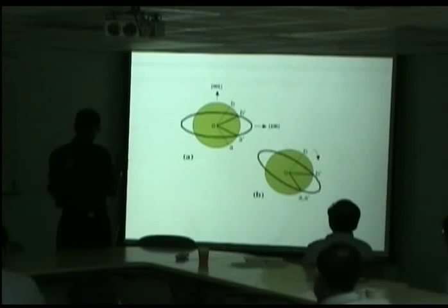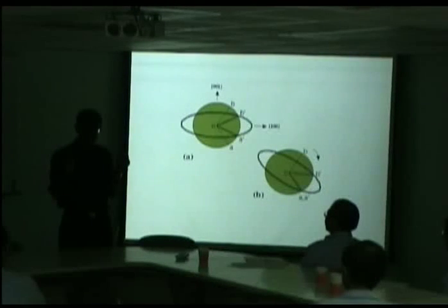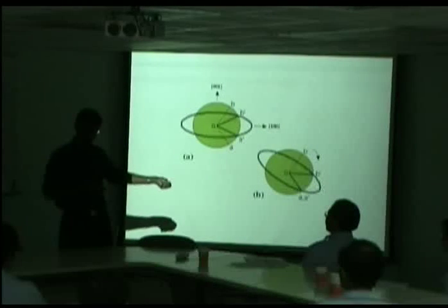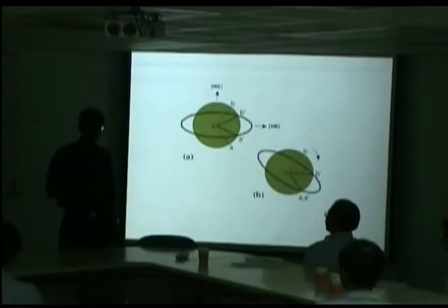But we only have one line coherent. In other words, I can't shear the austenite into martensite, because to shear, I would require a whole plane to be coherent. So there's still something wrong, because the shape change we see is a shear. But the Bain strain plus a rigid body rotation is not a shear deformation. It just leaves one line coherent.